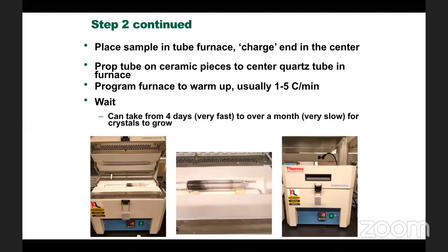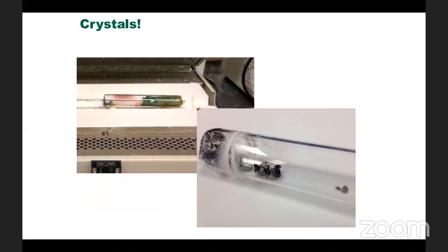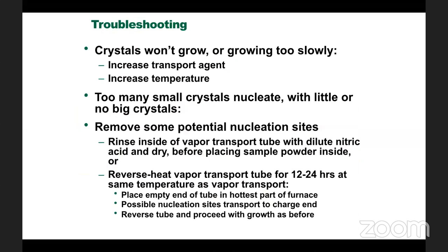So you can see here how they are maintaining. You can keep your ampoule inside the furnace, and you can set the temperature, and after maybe 10 days, you will get a very nice crystal. If it is not formed, we have to go to other alternatives. This is a grown crystal. If the crystal does not grow, maybe increase the transport agents or increase the temperature.